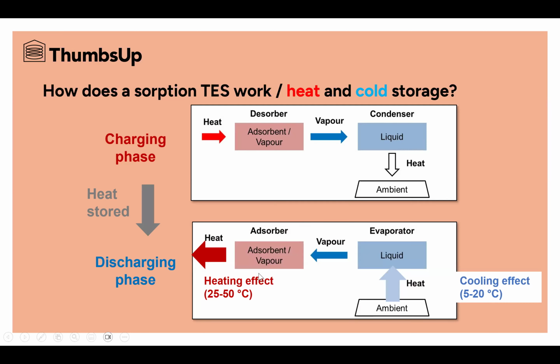During the discharging phase, we have two effects: cooling effect and heating effect. Cooling effect because the ambient supplies heat to the liquid in order to evaporate the water. The water transforms into vapor, the adsorbent material adsorbs this vapor and releases heat to heating, for example, water or the ambient of the building.